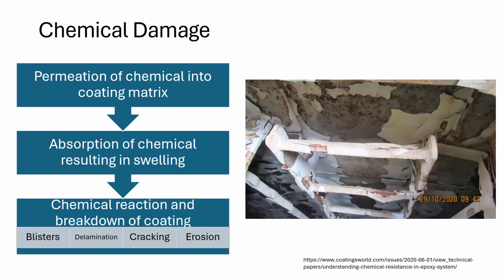So, I looked into some research. Definitely, I know what can happen if you put the wrong coating and the wrong chemical. But basically, what happens is first thing that happens is a permeation of the chemical into the coating. So the coating cross linkage is not good enough to handle the chemical, and it's going to start to permeate through the coating. Over time, the coating is going to absorb the chemical and result in swelling, which is going to result in blisters. Usually is the first thing that pops open. Then it goes to delamination and cracking. Something you see with strong acids at times is also erosion, so it might just erode the surface over time.